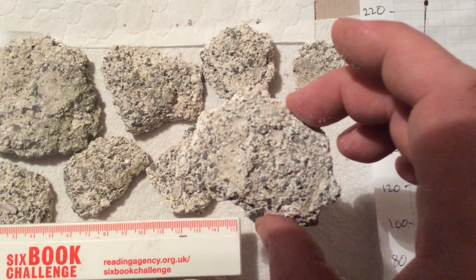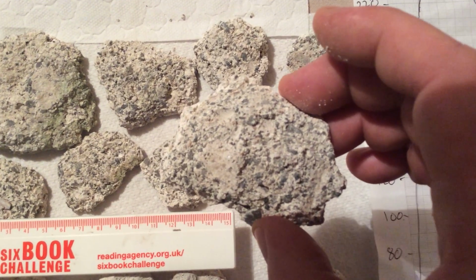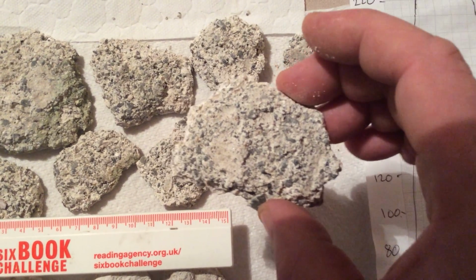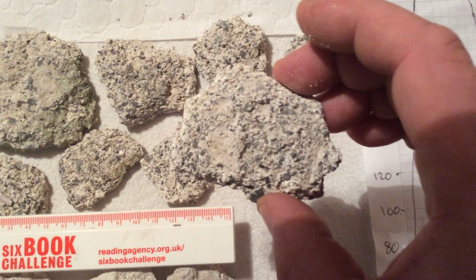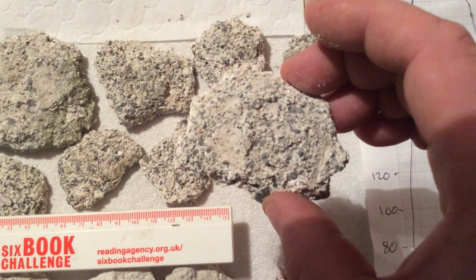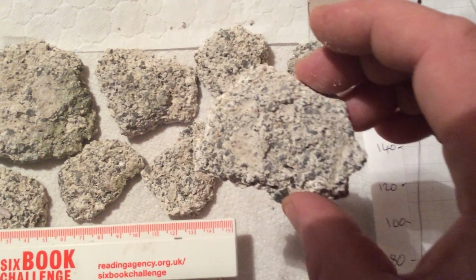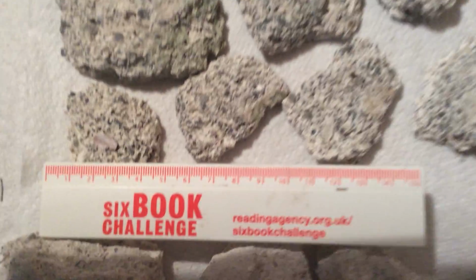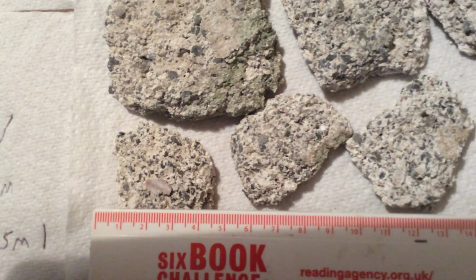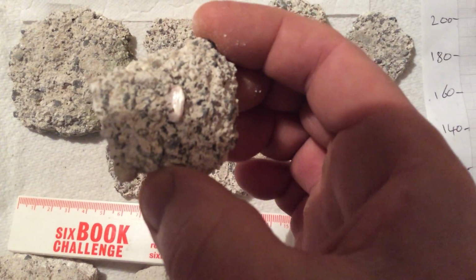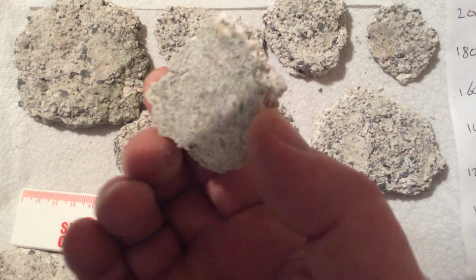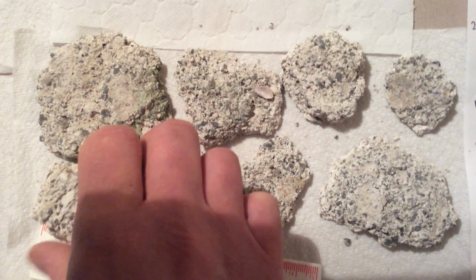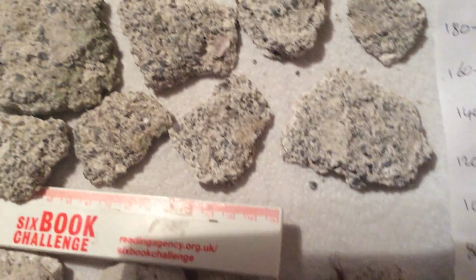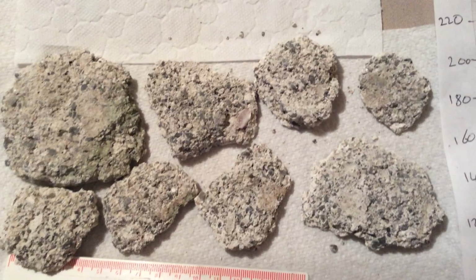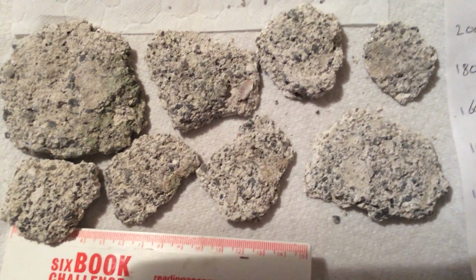So presumably it was hauled onto the surface at that thickness, and because of the impact, we're looking at the back of the coating, because of the impact, a lot of the pebbles or flat pebbles, platelets, are flat with their planes parallel to the wall. In this sample, bottom left, we see a seashell, slightly purple. And the material does crumble and fall apart very easily. So that's the outside material.